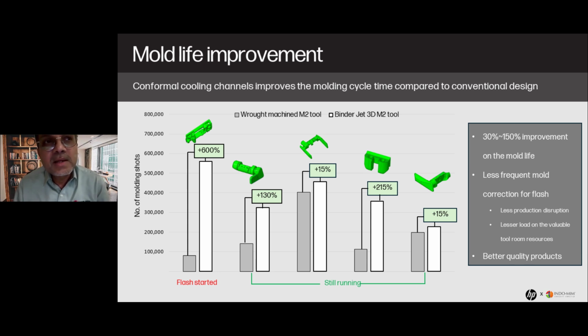The way we calculated the mold life also was: between starting off using the mold and the time where it starts flashing first, how many cycles the mold is able to run. Because each flash correction is a burden on the tool. The tool is pulled out and it goes to the tool room. You spend a lot of resources. To that extent, you don't have the mold in production. So it is really a pain point for us. So on the first tool that actually completed its life, we were able to achieve almost 600% improvement in the mold life.